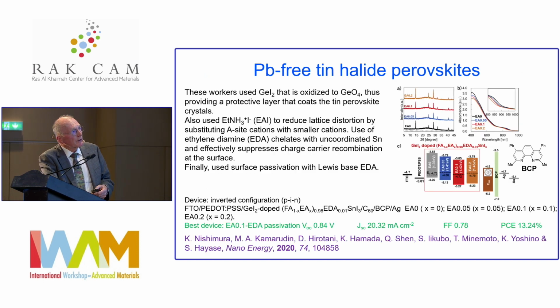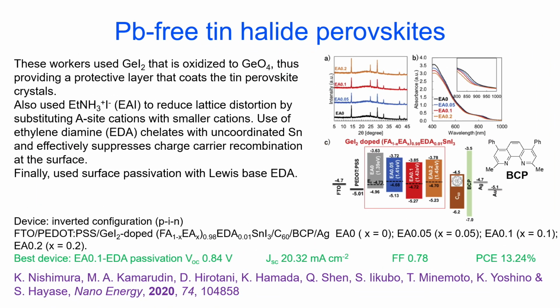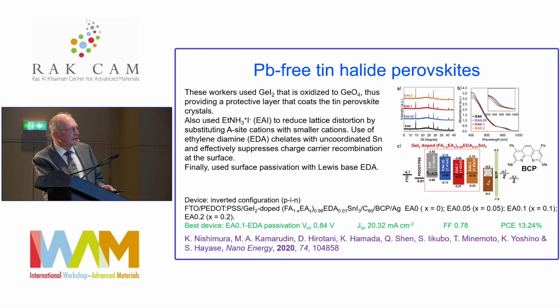But the best result, I think, that's been achieved with a tin halide perovskite is one that used ethylammonium iodide and ethylene diamine to coordinate uncoordinated tin and suppress charge carrier recombination at the surface. And they also used ethylene diamine to passivate the surface, as I've just mentioned. The optimum result is the combination where x is 0.1 in this formula of the formamidinium combined with that 0.1 EDA tin iodide in the perovskite layer.